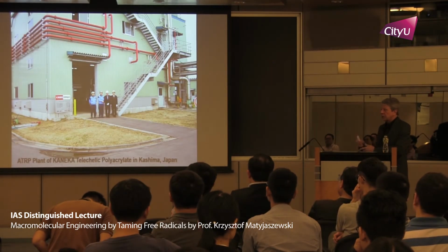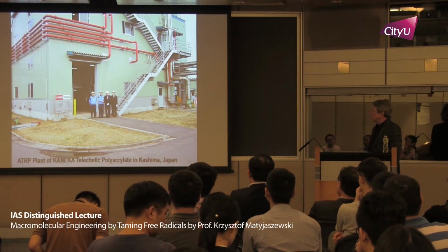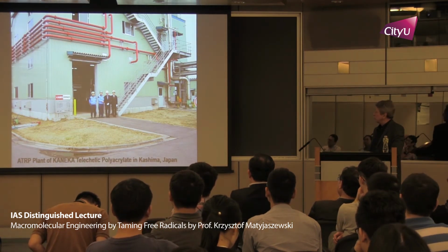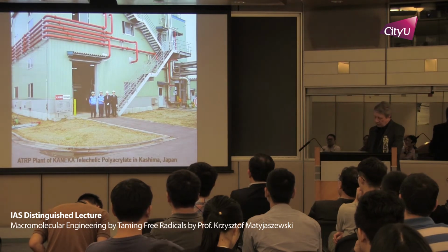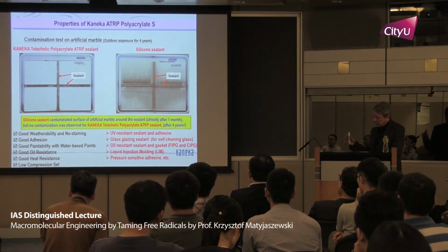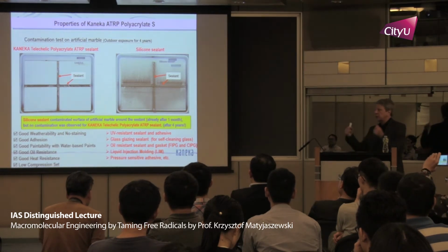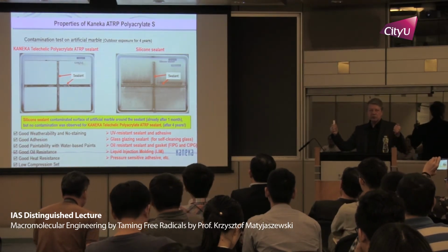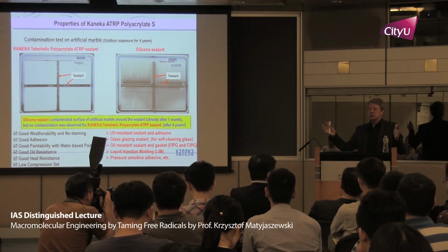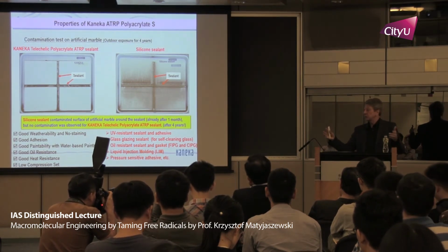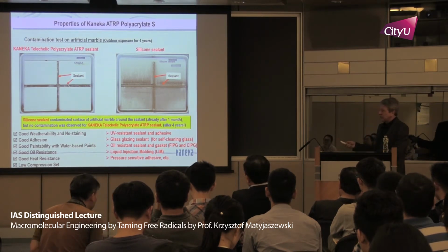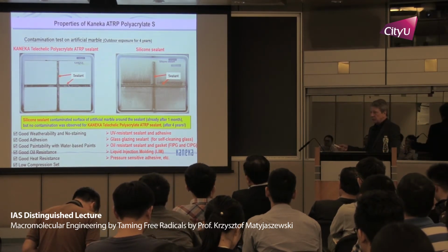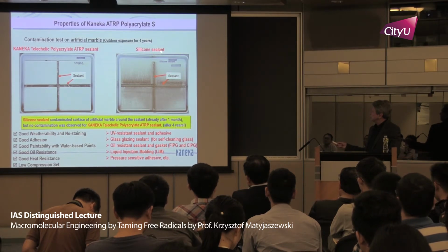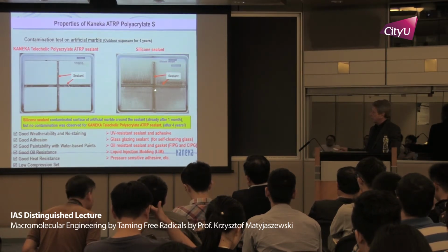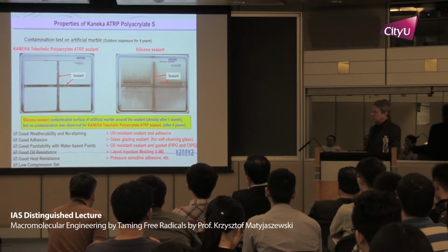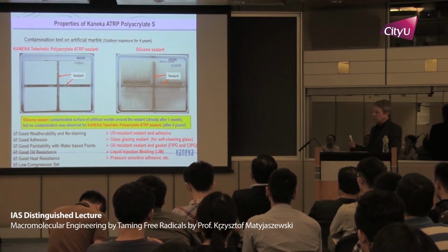Our first real collaborator in this area was Kaneka in Japan, and they had this small pilot plant originally in Kashima, Japan. They do that mostly for sealants. So they are polybutyl acrylates, roughly speaking 10,000 molecular weight, with 2 functionalities which can be either UV curable or sometimes moisture curable. So these are examples of these sealants. And for comparison, this is a classical silicone sealant. This is after 1 month, and this is after 4 years. So dramatically better behavior, for several reasons.